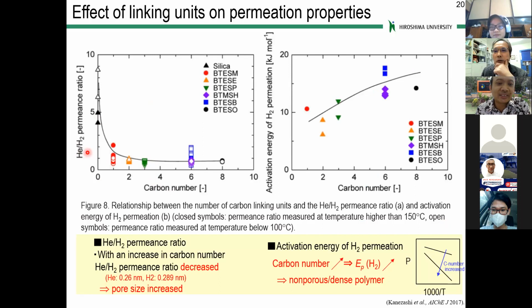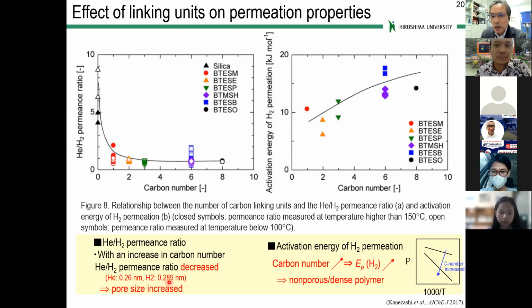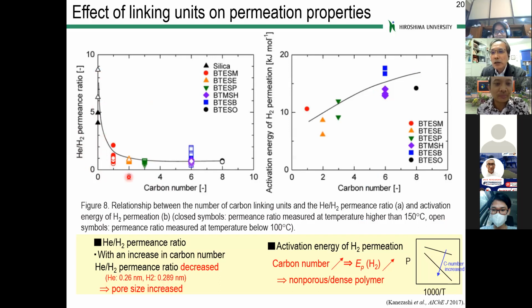Actually, this is the helium over hydrogen. The size of helium is 2.6 angstroms, the smallest, and hydrogen is 2.89. So at carbon number 0, this is just like a silica-derived membrane. We can fabricate membranes with small pores without the linking group. With adding the linking group, the network pore size increases, which allows higher permeation of even hydrogen, so the permselectivity decreases a lot. So we concluded the pore size increases with increasing carbon number. That is the concept, and when we proposed the spacer method, this is the trend we expected.